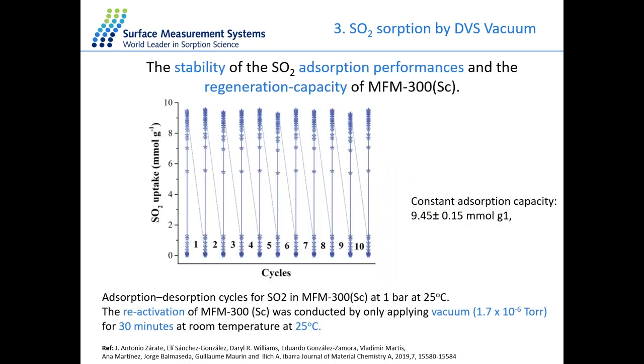We also look at the stability of this MOF material with a cycling experiment for SO2 sorption performance. So we cycle the same MOF material under high vacuum 10 different times. The regeneration step of this material is under vacuum at 25 degrees for 30 minutes. And then we introduce pure SO2 gas for cycling.